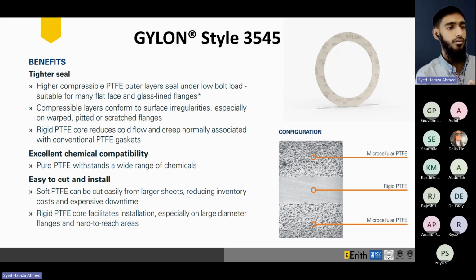So this provides an added advantage when you're using glass lined flanges, since the microcellular PTFE is highly compressible. And these outer microcellular PTFE layers get compressed under low bolt loads and seal between the glass lined flanges, as well as the rigid PTFE core reduces the cold flow and creep that is associated with conventional PTFE gaskets. So this Gylon style 3545 is a best fit for glass lined flanges. This is added with the excellent chemical compatibility of pure PTFE.